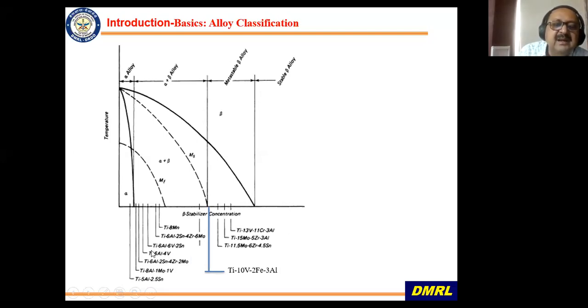And then there are other alloys which are for high temperature application, which also belong to the category of near alpha titanium alloys. And then when you cross the martensitic start line, as I said, you go into the beta alloys. The first one of the alloys which is very widely used is titanium 10 vanadium 2 iron 3Al. It is one of the metastable alloys that Boeing uses for landing gears and other applications, very widely used.